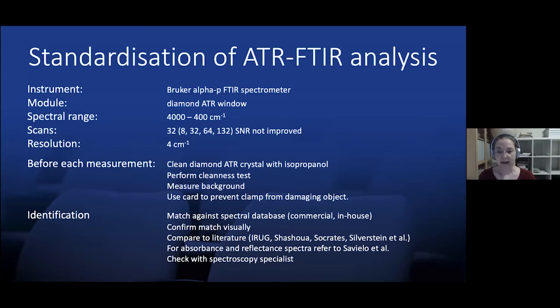We also had a process that we do before every single sample. So we always measure the background, and also just a little tip, if you want to minimize damaging your sample, you put a card on top in between the sample and the clamp to minimize any damage to the object. In terms of identification, we used the commercial and our in-house database. We made sure we verified our matches visually, we compared to the literature, and we also double-checked with the spectroscopy specialists that are part of the project.